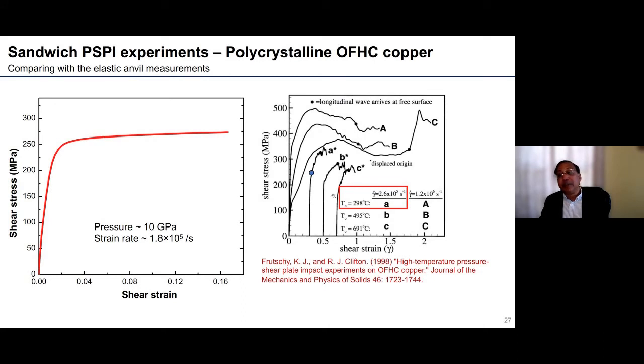These are results from Clifton's experiments with Frutschy. Here this is plotted shear stress as a function of shear strain. And here you can see what is denoted as A. Here it's at the ambient temperature, and the strain rate is pretty close to what we have. So the values are comparable. It's about 260 MPa or so at this nominal pressure of 10 GPa.